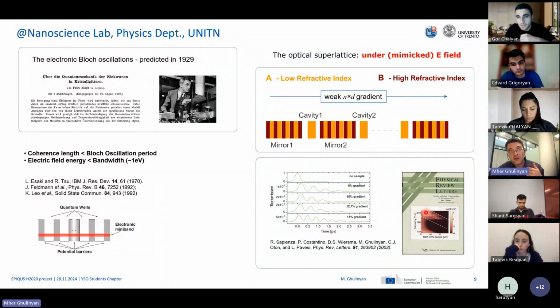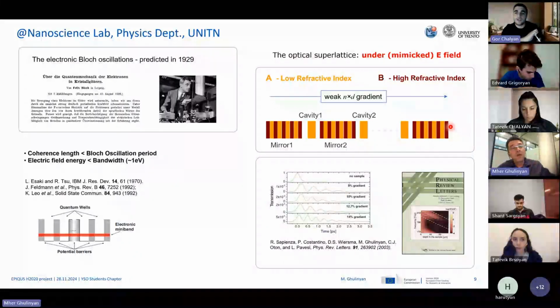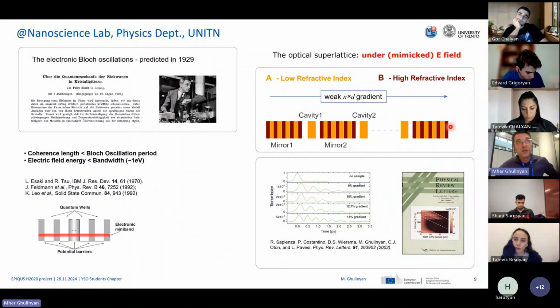You see this image. All these horizontal lines are the energies of the different cavities, and they are at different positions inside the sample. So the last cavity is quite different from the first cavity, but having a tiny gradient between each other makes them couple everything. So this is the concept. The gradient is applied on all dark brown layers, on all mirror constituent yellowish layers, and also on all the cavities. So they have all the same gradient. Oh, okay. So you tilt everything, let's say, kind of linearly. Otherwise, you will get a very crazy form of the bands, which is not a good idea.